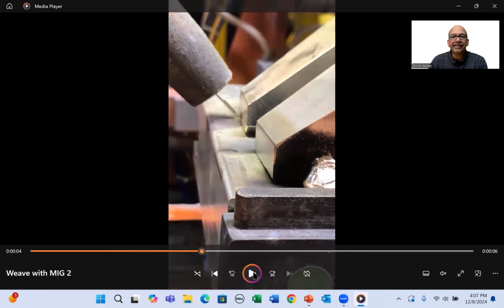So here we can see that the gun has approached the starting point of the weld. The wire is extended. Again, if this were a live actual welding video, you would have seen a very intense arc over here. And the arc is hot enough to melt a little bit of both the base metals as well as the wire, and it forms the fillet. It starts from the starting point, then it traverses along the length of the component, and then it retracts.